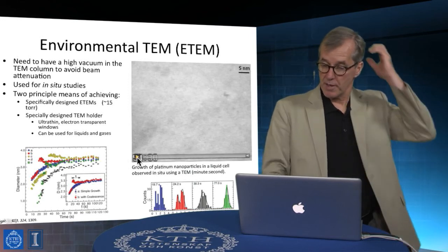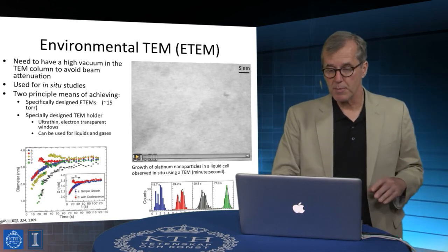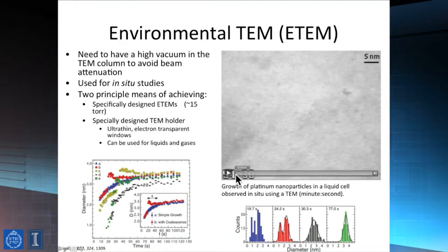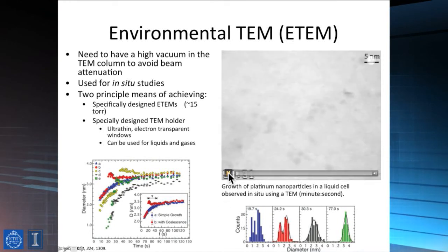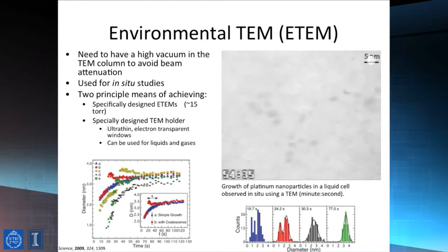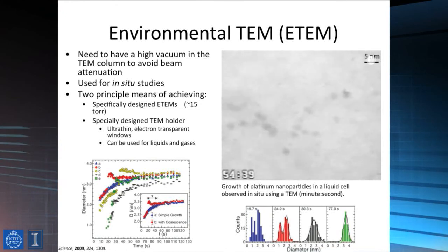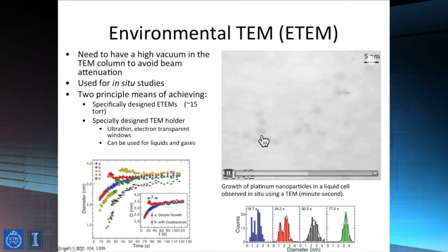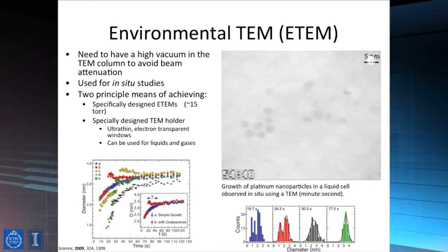Measurements can also be done in environmental context. Now, this is going to be a hard-to-see movie, but it's a great one. What's being done in this particular case, if you look at this, you'll see little things swimming around, and it will grow progressively darker, and the dark things will actually start to become bigger. You'll see, for example, right here, one of the dark things becomes a little bit, now they're coarsening and becoming bigger. This is actually nanoscale imaging that's being done in aqueous solution.